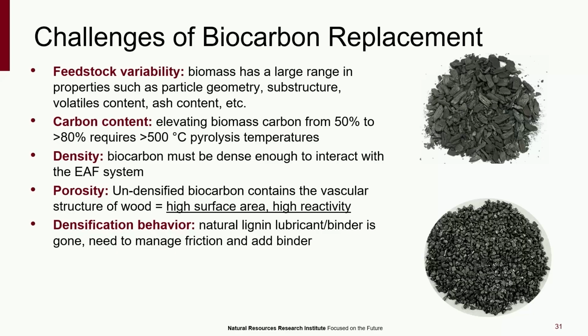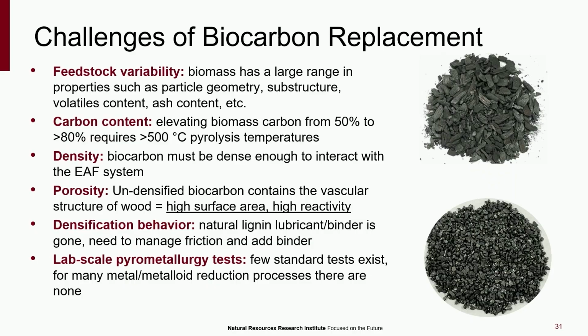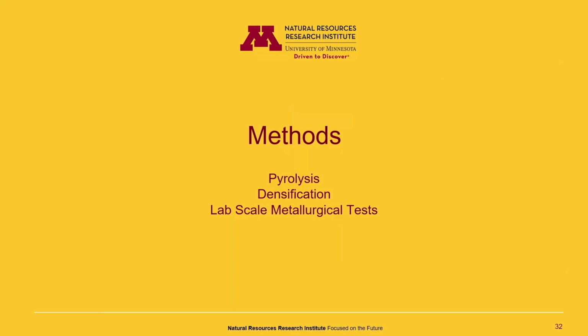We can't actually densify without adding additives back in. So that natural lubricant or lignin that's in wood or other biomass for pelletizing or densification is no longer there after pyrolysis. So we needed to figure out a way for it to stick together. And then also we needed a way to validate these formulations at the lab scale. Right now, there's no actual standard test that exists to know how this is going to perform in an EAF. We wanted to know that these formulations would work before we went up to the 10 to 20 ton trials. So next, I'll move into our methods.